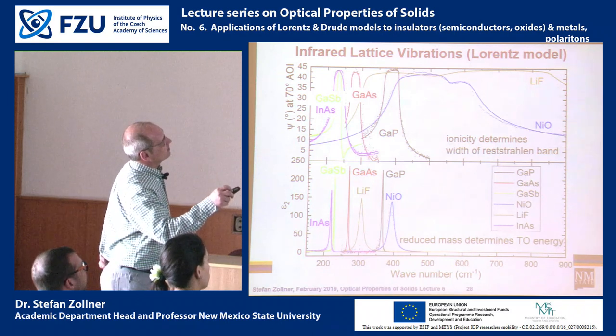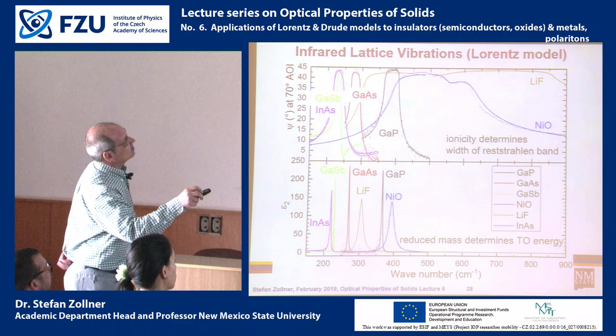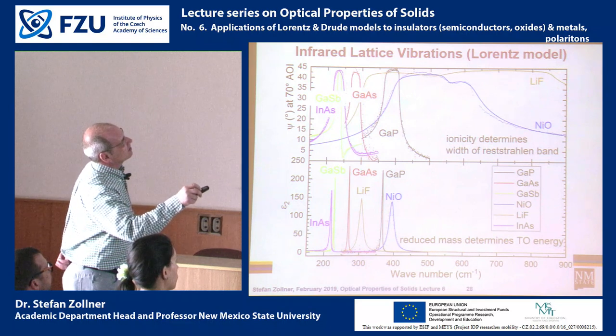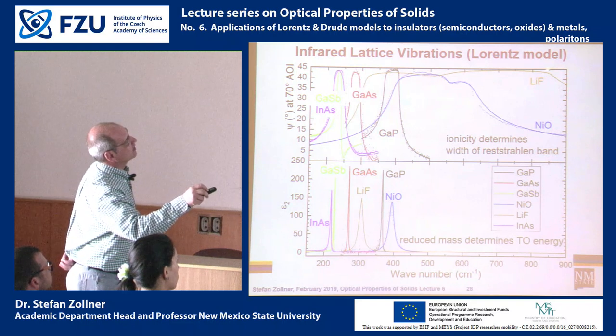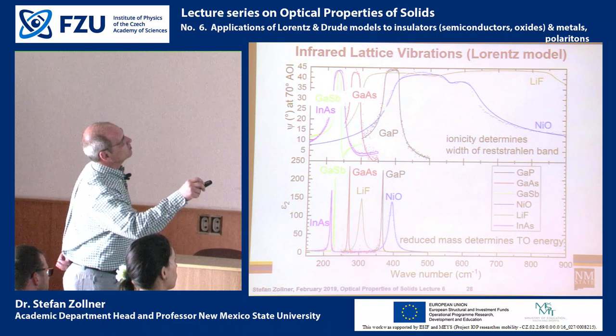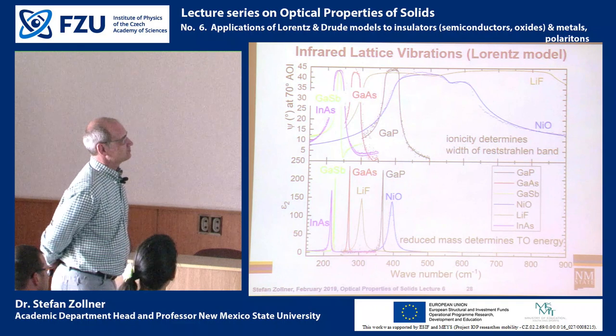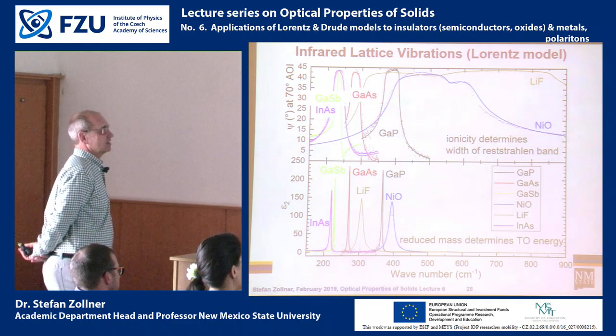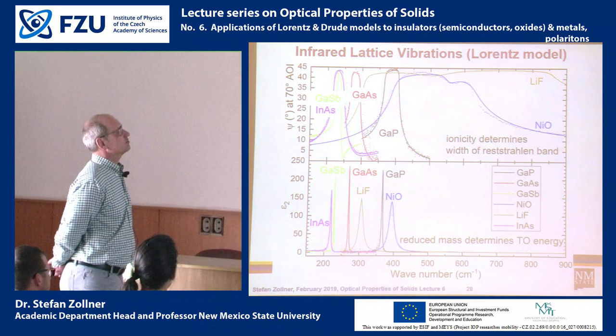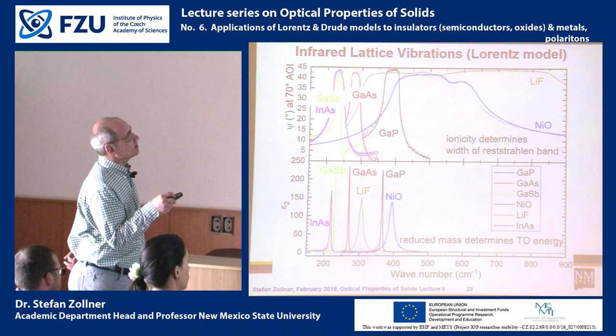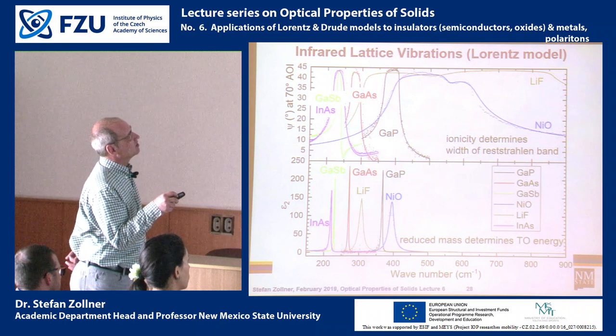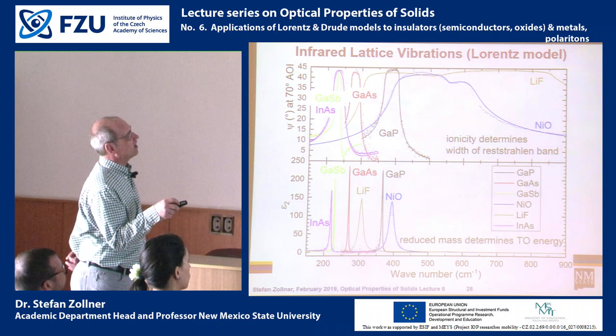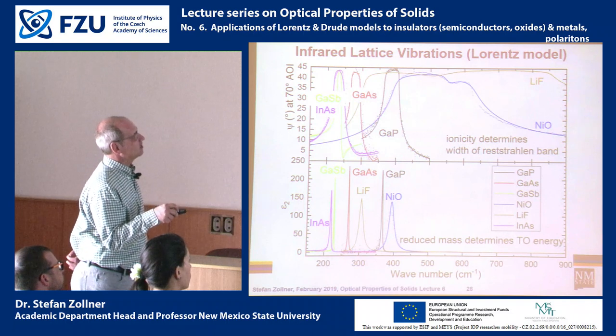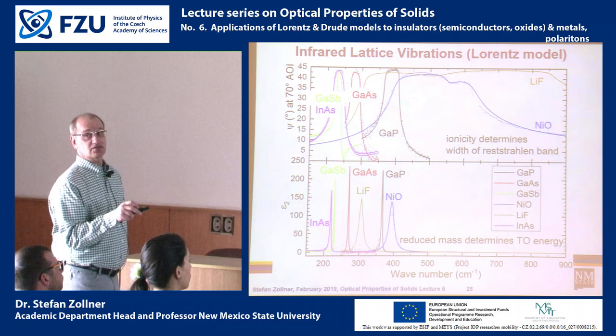So in lithium fluoride, the splitting between the TO frequency, which is here, and the LO frequency, which is there, is huge because the Born effective charge is huge. In nickel oxide, we also see a rather large splitting between the TO and LO frequency, because nickel oxide is also more ionic than gallium phosphide. So the ionicity of the bond determines the width of the Reststrahlenband, the separation between TO and LO, and where the resonance frequency is, that is determined by the reduced mass.